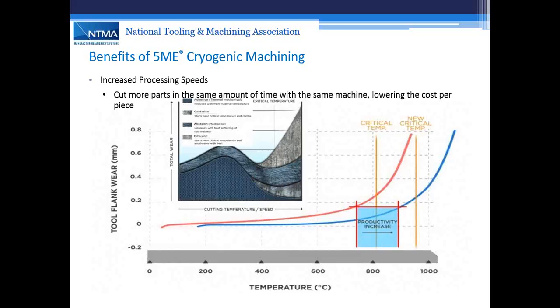Okay, looking at the base graph that we have here, the vertical axis is tool wear, flank wear, and the horizontal axis is temperature. And temperature is related to speed, of course. They're not linear, but related. If we look at the first plot of the red line, that looks at what carbon steel machining looks like with carbide. And it says that the faster I machine, or the higher the heat in the shear plane is, the higher my tool wear is.